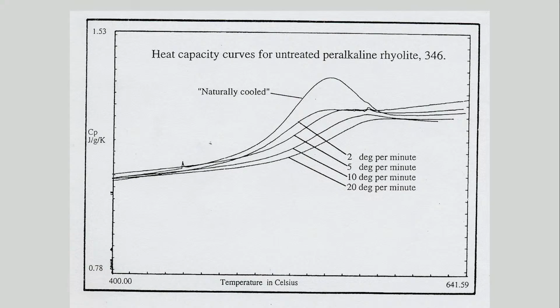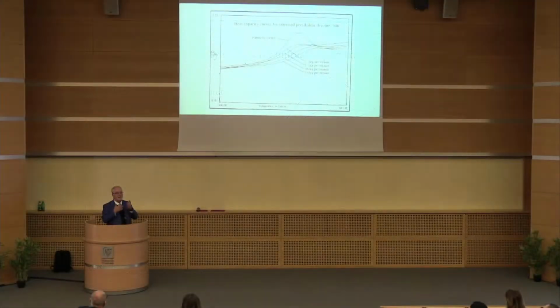And then we fit this to a kinetic model, and then we solve for the original curve that we got on this sample, which is the first curve we received after we took it out of the field and heated it up. Because glasses have a thermal history. They actually record the cooling rate at which they were produced.